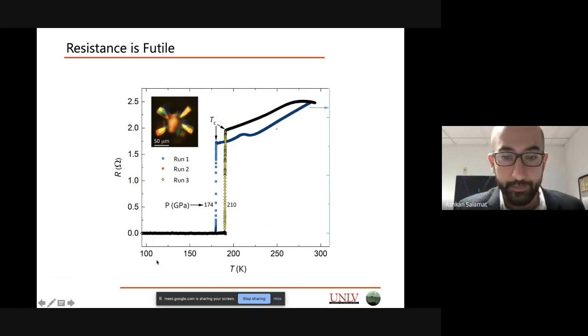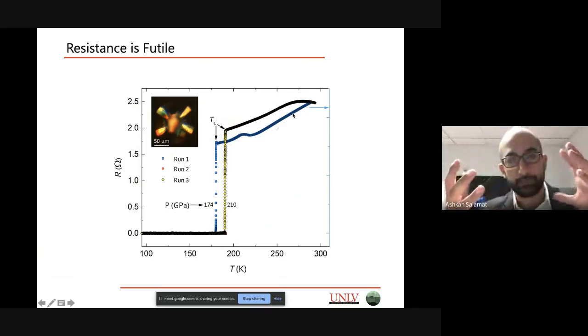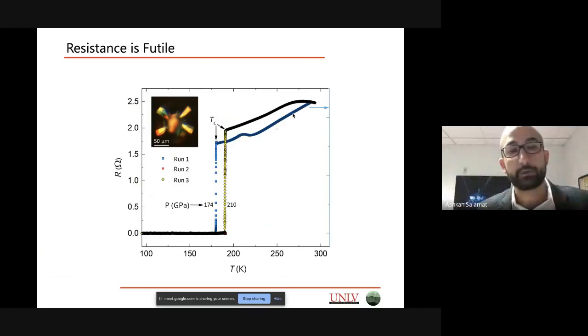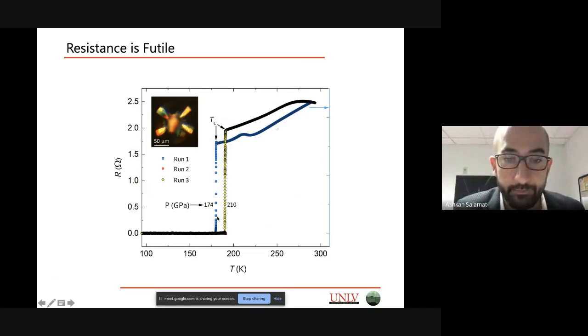At the bottom, I have temperature, and on the side here, on my y-axis, I have resistance. So what happens if we follow just the blue curve here? You cool the material down, and as the atoms slow down in the metal, the resistance is lowered. The electrons can flow more easily from A to B. At some critical temperature, there is a sharp, dramatic downturn to zero resistance. This is indicative of a superconducting transition. One of the hallmark properties of superconductivity is zero resistance to electrical flow.